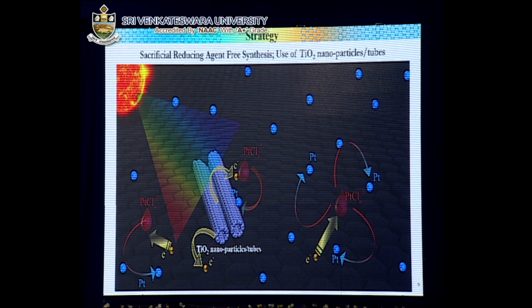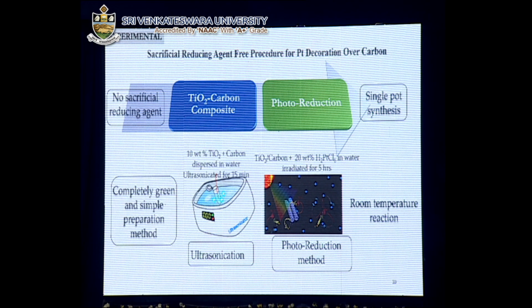So this is the concept, and now I'll show you the results which will prove that this is possible in the manufacturing sector also. Before going to that, here is a simple schematic of what we do exactly. This is a two-step process where we mix the TiO2 and the carbon by ultrasonication, and then we irradiate with UV light, or normal visible light is also sufficient because it has enough UV to excite the TiO2. And once this is done, we get the composite electrocatalyst.